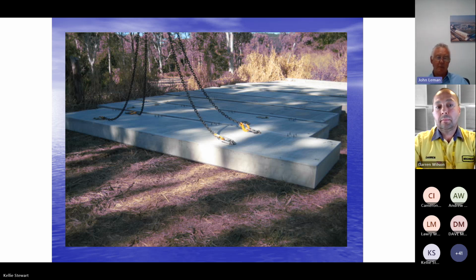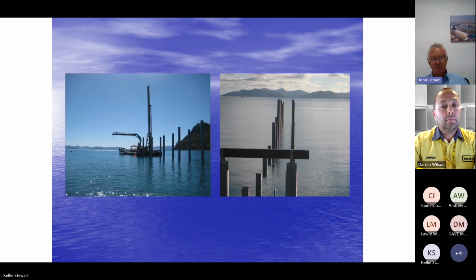Here was just the outer part of the jetty and driving piles with a 2.5 ton drop hammer, and they were dropping it up to 1 metre where they struck some sort of coral objects in the bed and had to get them in. Where they did get some serious resistance, they were really belting these things, and it's amazing how well they stood up to the hiding that they were getting. So you can see that picture on the right. They're all looking pretty good, the tops of those piles.